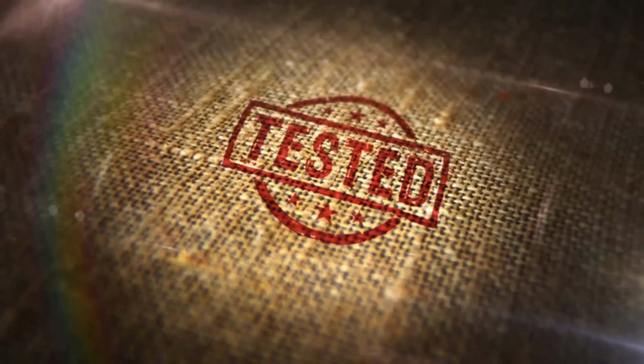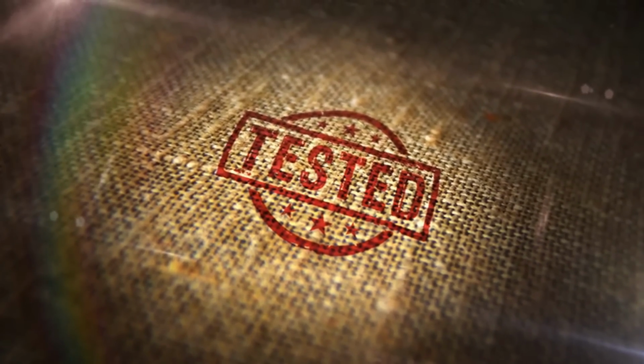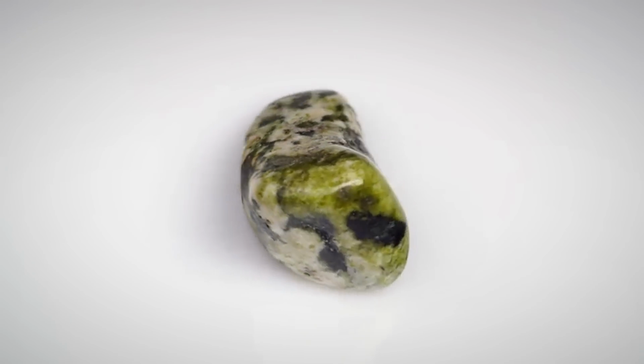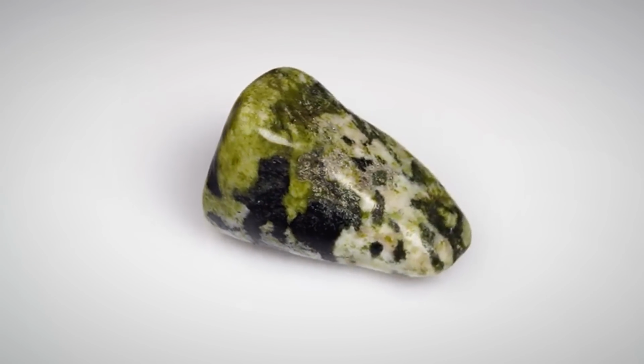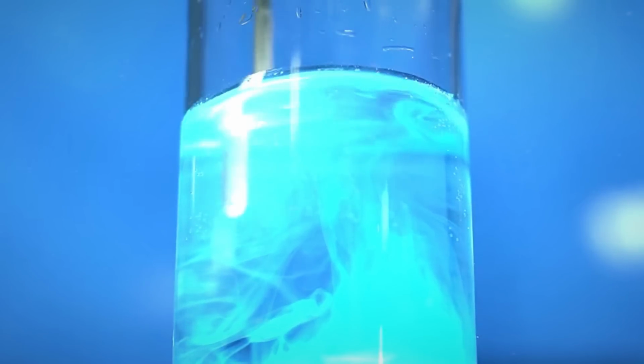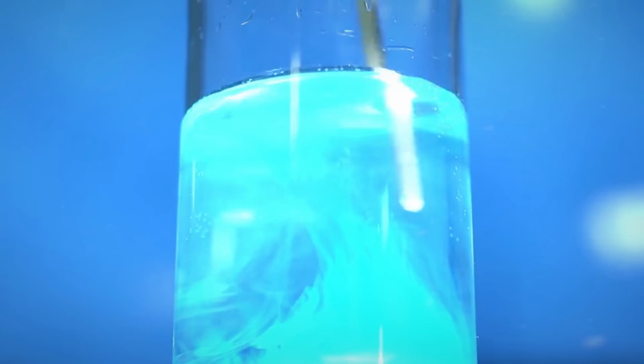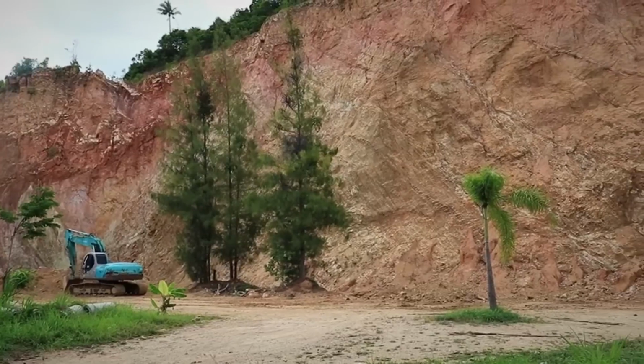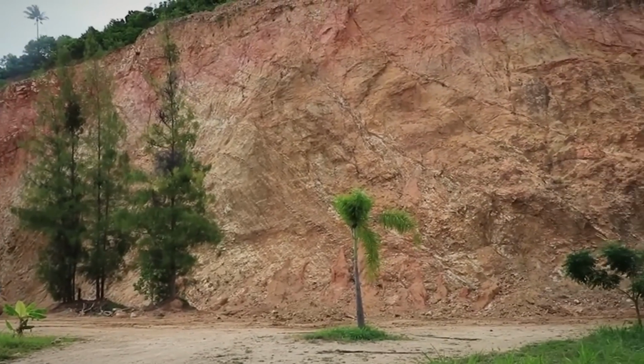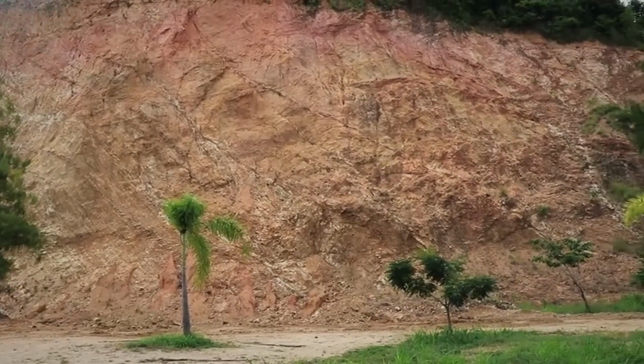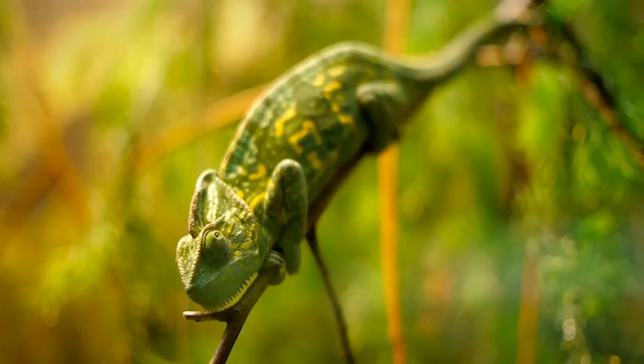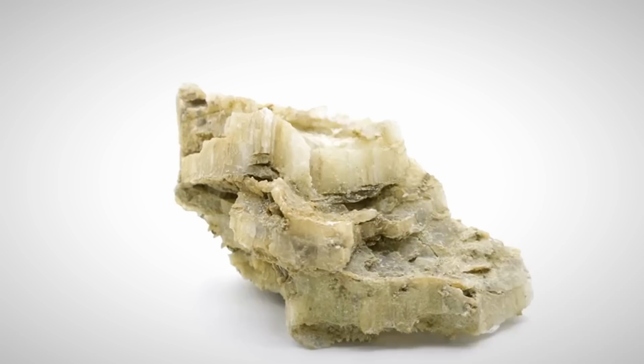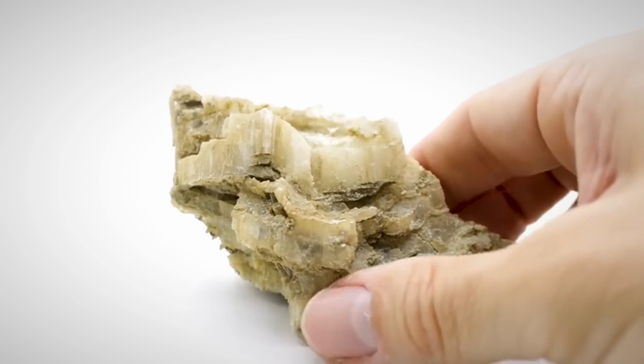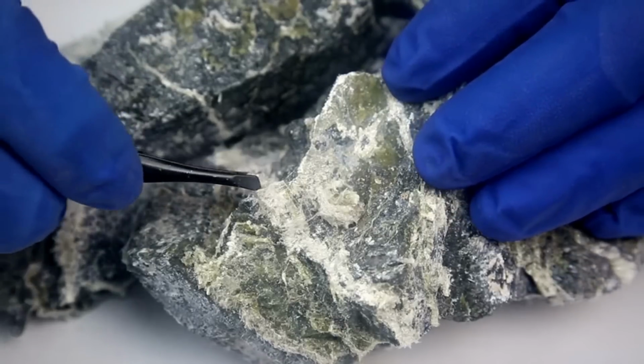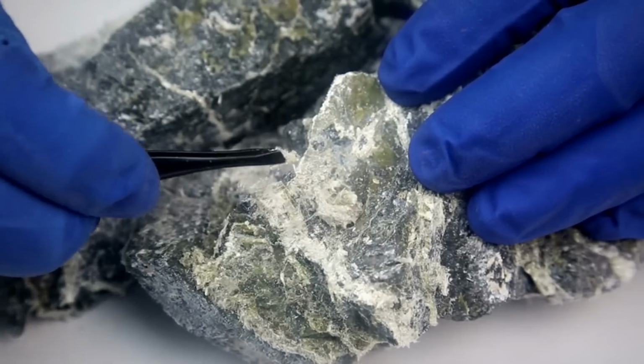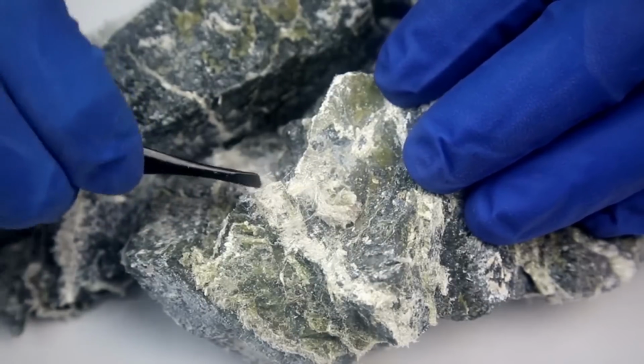From a distance, it gleamed with the same muted intensity, a semi-translucent chunk, pale green in some light, milky in others. To the untrained eye, it mirrored the subtle luster of a raw diamond. But as the field tests began to contradict each other, the truth became clear. It wasn't a diamond at all. It was nephrite, a form of jade, misread due to its mass, color, and context. And in other cases, it's opal, hydrated silica with just enough heft and glow to fool a thermal test. These are the geological imposters, and they can mislead even well-executed sampling campaigns if you're not tuned to their environments.